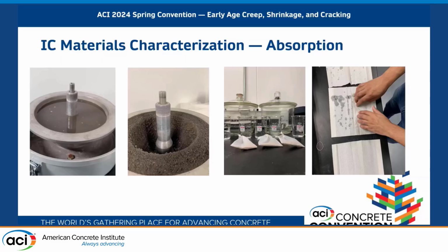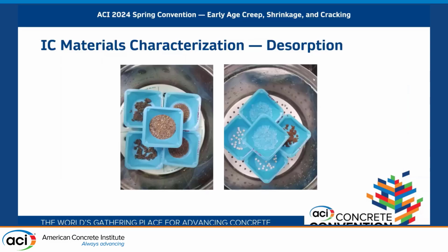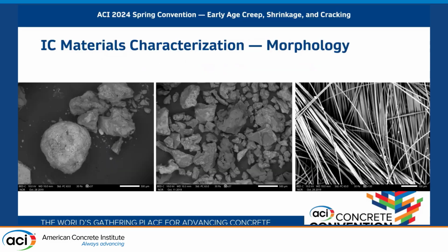So we looked at that, and ultimately, like I said, we started screening materials based on the absorption and desorption characteristics. We also did morphological studies on the shape of the material. So from left to right, we have a lightweight aggregate, a superabsorbent polymer, and some fibers that were evaluated.